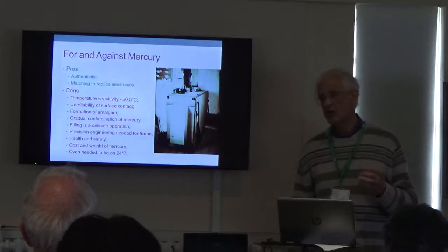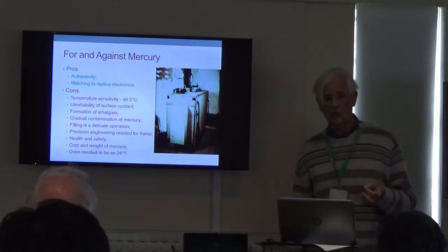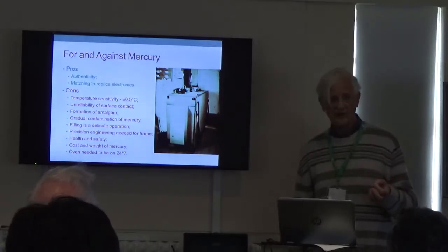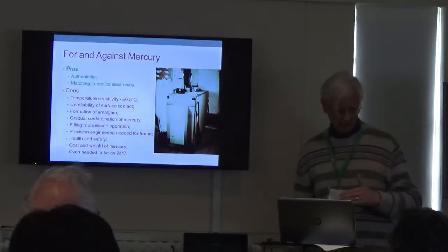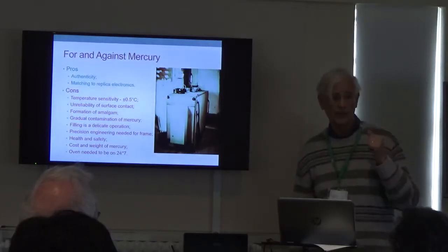So the procedure was to fill the tank with a suitable liquid, originally alcohol and then I think glycol later, which you then displace by pouring in the mercury very slowly, and if you're lucky, the mercury will wet the quartz crystals.